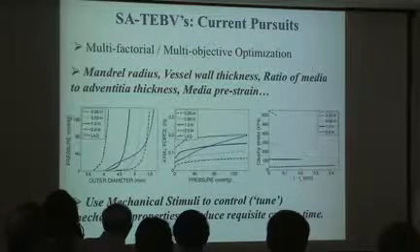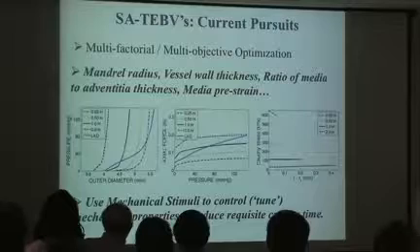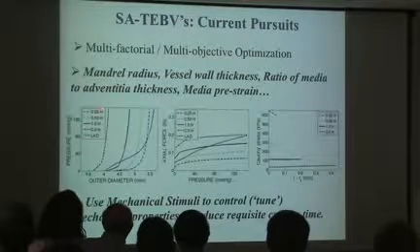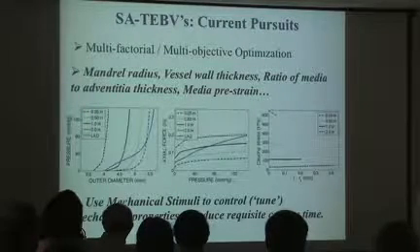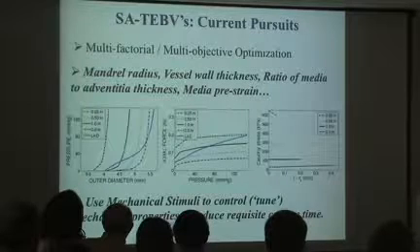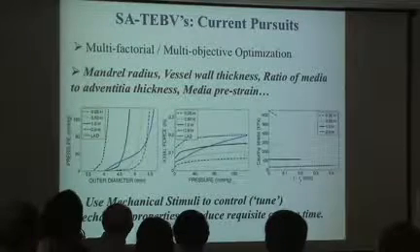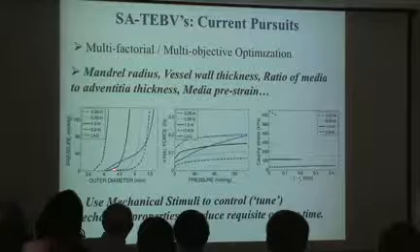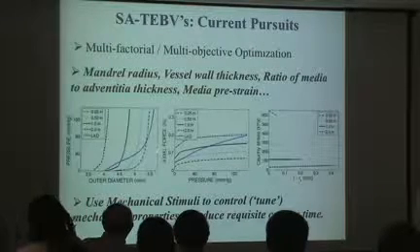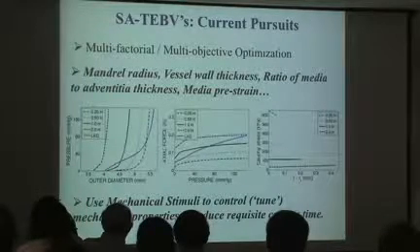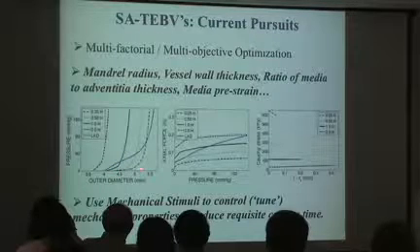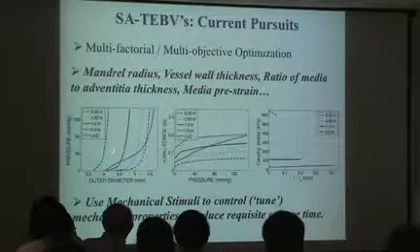This is actually a little bit of a counterintuitive result. We cut the thickness by a quarter, right? When we reduce the thickness of a vessel, we expect it to be more compliant, right? In fact, it is more compliant. It distends from, say, 4.4 all the way up to maybe 5.4. So the overall distension of the vessel is a lot more than for the very thick vessels.